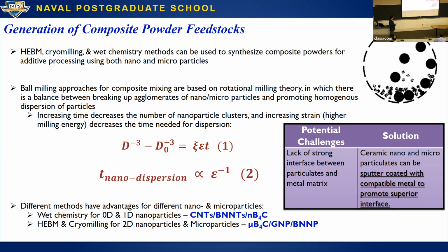Here, we're trying to break up powders, and I'll show you in a couple of slides that nanomaterial powders, if you're not familiar with them, you usually buy in an agglomerated form. So we have to break that up in the first place, and then we have to disperse them. The more strain you impart on the system, the better the dispersion, but there's a balance between how much strain you impart and how much potential damage you do to the nanoparticles, which you're trying to keep in a pristine state.